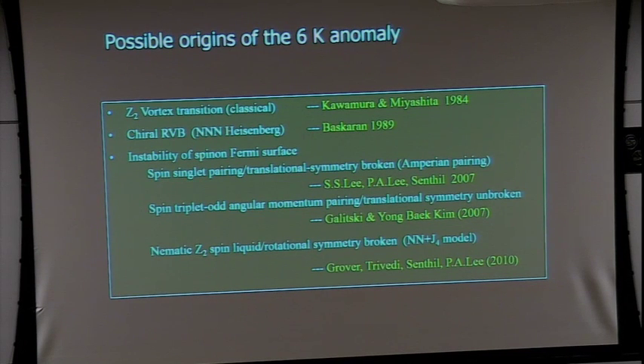But some theoretical suggestions may be relevant to these anomalies. Among them, the instability of the spinon Fermi surface is one conceivable candidate. As I explained yesterday, the degenerate system with a Fermi surface is unstable because the degeneracy is inherently very weak against any perturbations. So if the spinon Fermi surface is formed, this spinon Fermi surface is likely to be destroyed by some other perturbation or interaction between the constituent particles. So several spinon Fermi surface instabilities are suggested, like superconductivity.